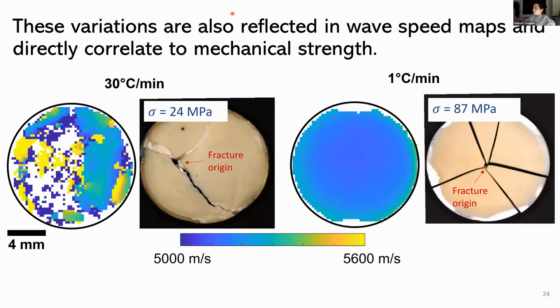You can see that a little bit more clearly here. So again, these are just the wave speed maps, but you saw the attenuation maps in the previous slide. You can see, even from the fracture patterns and from what's left over as the sample is fracturing, that the mechanical strength of the samples, in quantitative value, wasn't nearly as good as when we decreased that heating rate.